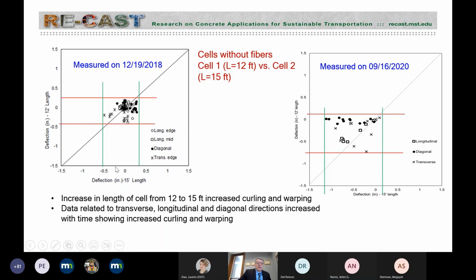We could see over here that for the 15-foot long panel, the difference between these two vertical lines is slightly higher than that of the 12-foot panel. That means warping and curling were higher in the 15-foot panel than the 12-foot panel. And that increased also with time. So we did this in December 2018, and we did this in September 2020. And we see with time that the difference between the vertical two lines for the 15-foot panels increases. Okay. So indicating again a higher amount of curling and warping with the 15-foot panel versus 12-foot panels.